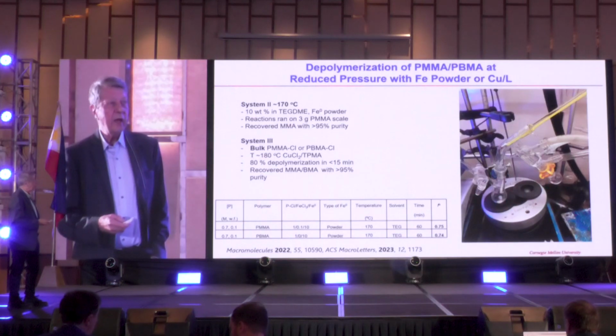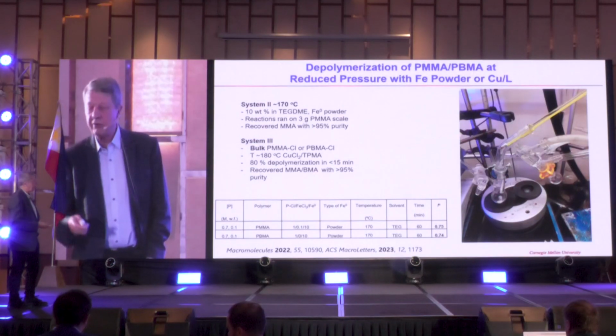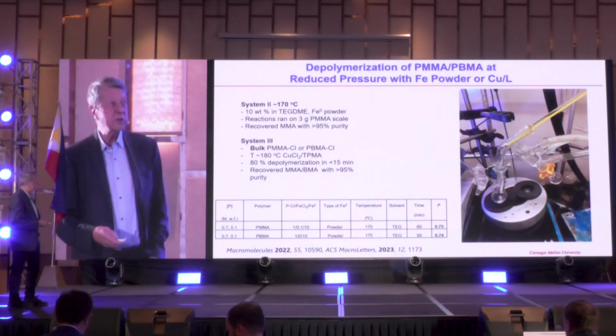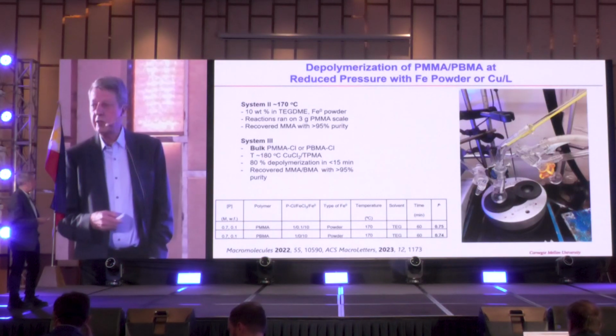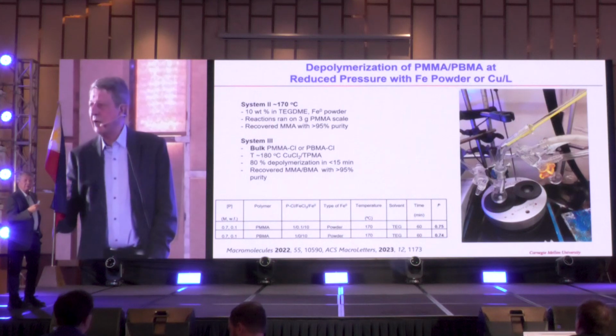So here's an example of taking this polymethyl methacrylate and exposing that to 170 degrees, not 500 degrees. And in that case, you could see that you can get methyl methacrylate with 95% purity in the presence of iron filings, just iron powder. Or you can take a bulk polymethyl methacrylate, 180 degrees, and 80% depolymerization in 15 minutes, and high purity monomer.